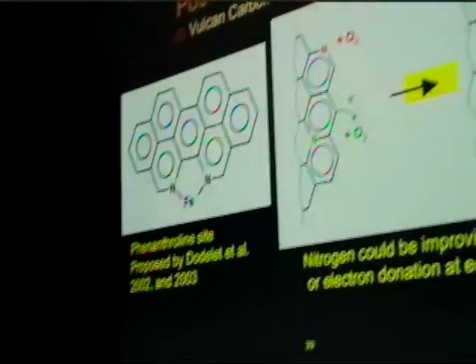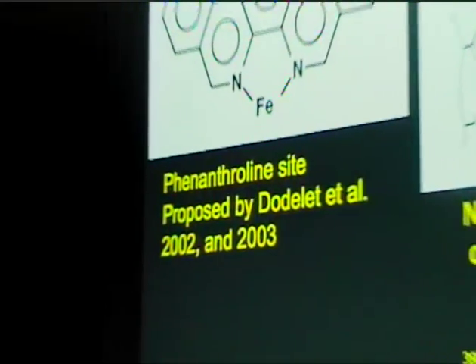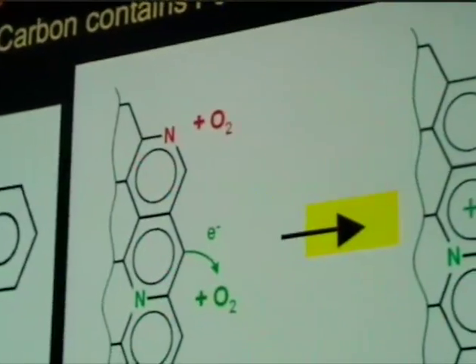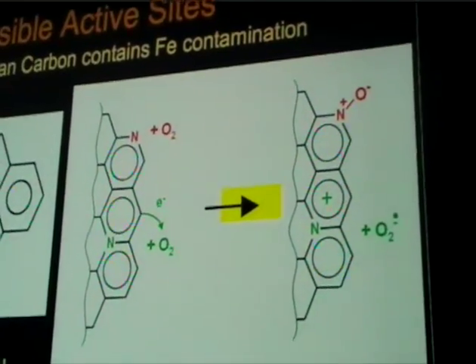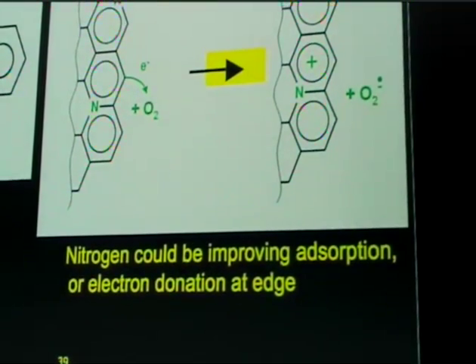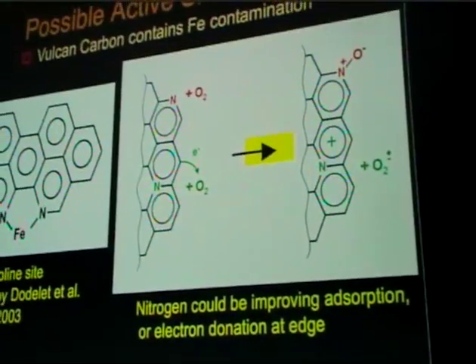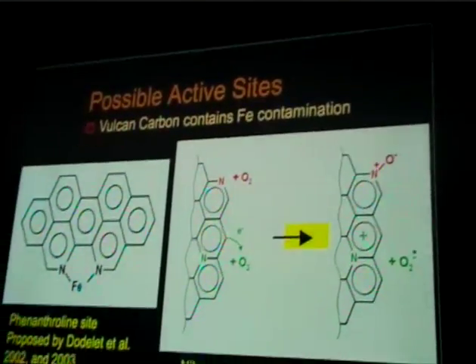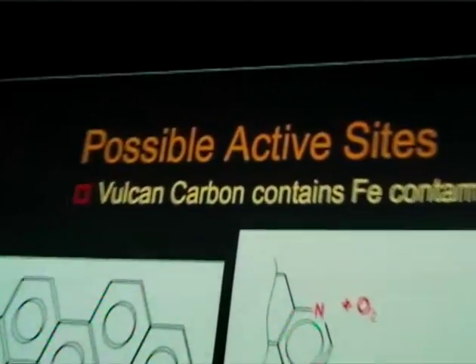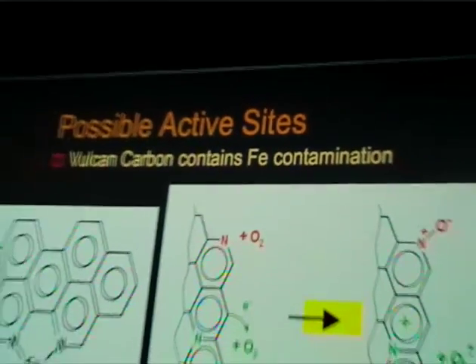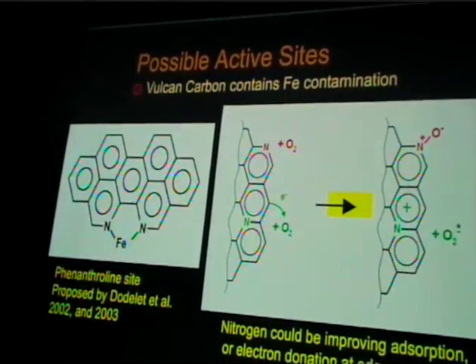Now again, there is debate, of course, about what the active site could be. So at this point, we were still faced with the question of, is iron really playing a role? Because as I said earlier, there is evidence reported in the literature about the presence of phenanthroline type sites which could have oxygen reduction activity.